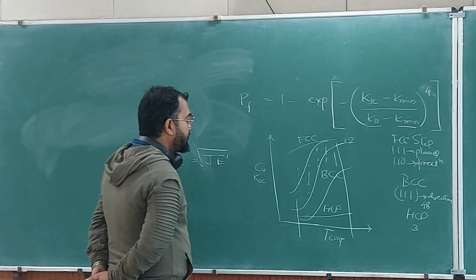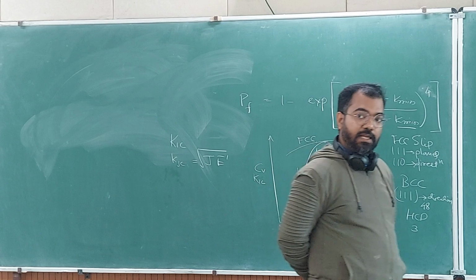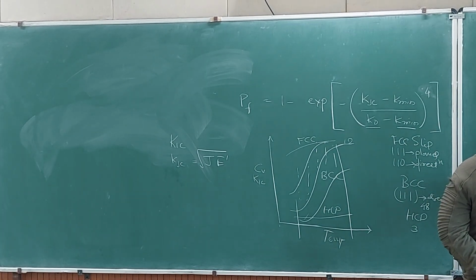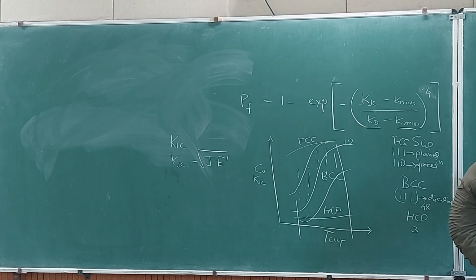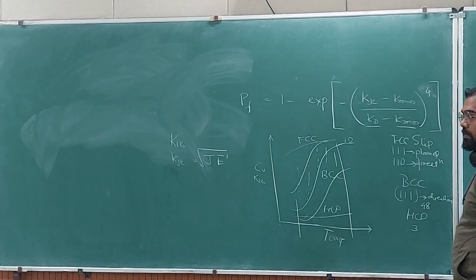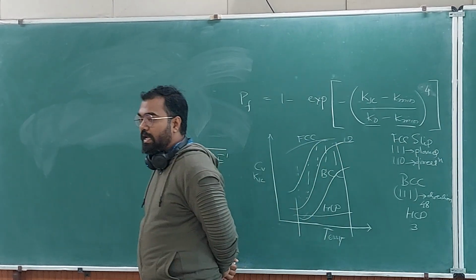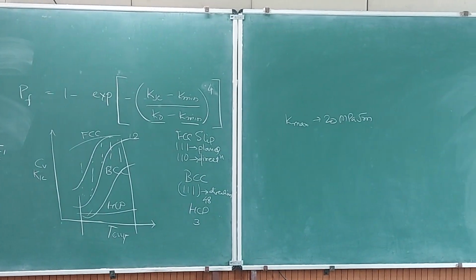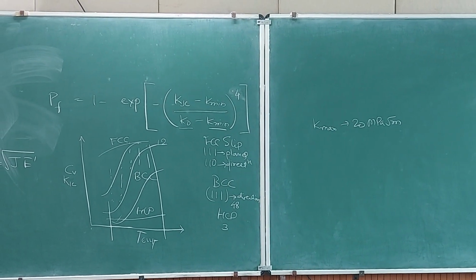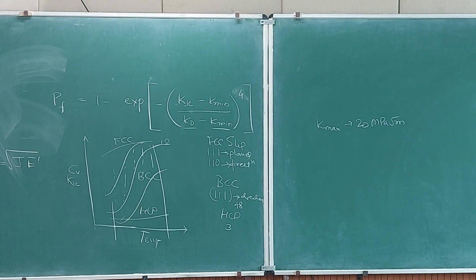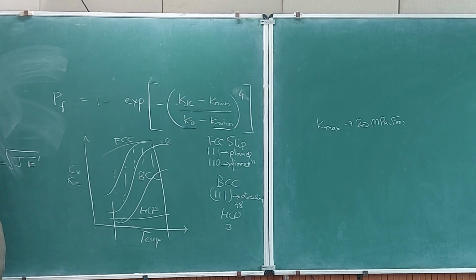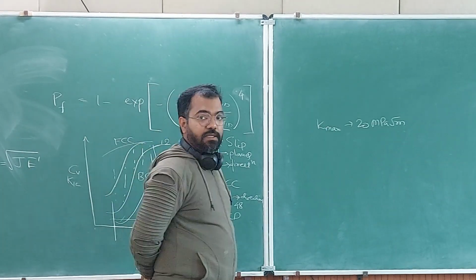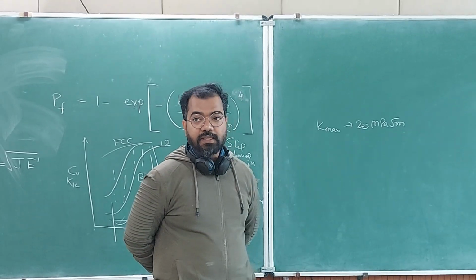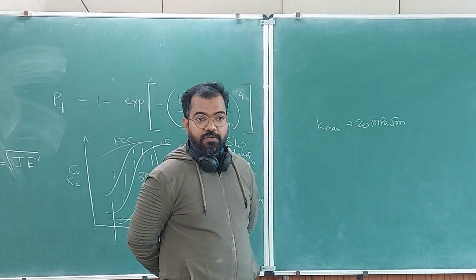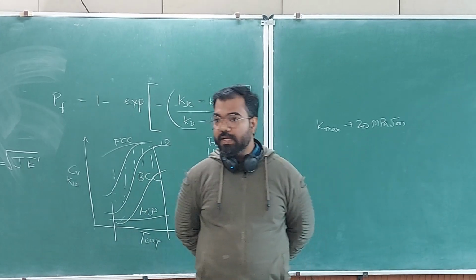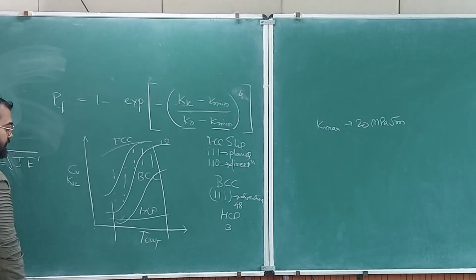People found that while doing the testing, they do fatigue pre-cracking, and in that fatigue pre-cracking, the K max goes to 20 MPa root meter. Although that is happening at room temperature, not at lower temperature, the fatigue pre-cracking can go higher than 20 MPa root meter. So after a lot of analysis, people arrived at the value that if K1C or KJC is lower than 20, then we don't expect the material to fail. So that is hitting the lower shelf. In the lower shelf, you don't have much scatter here.